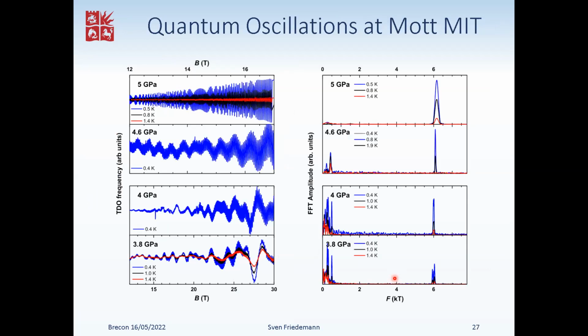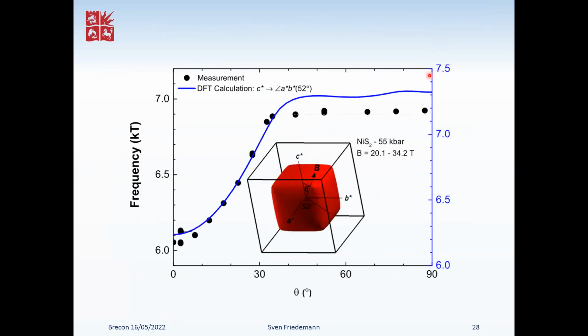So we can do this at high pressures, and we do see quite beautiful quantum oscillations in nickel disulfide. We start with a sample which is, of course, insulating at ambient pressure, but once we go into the metallic phase, we see beautiful quantum oscillations. It's the frequency of the tunnel diode which shows these oscillations, but as I said, this is proportional to the resistivity. The Fourier transforms show us some nice high frequencies of the order of 6 kilotesla, as well as some low frequencies. This highest frequency is easiest to understand. It corresponds quite clearly to a cube-like Fermi surface in nickel disulfide.